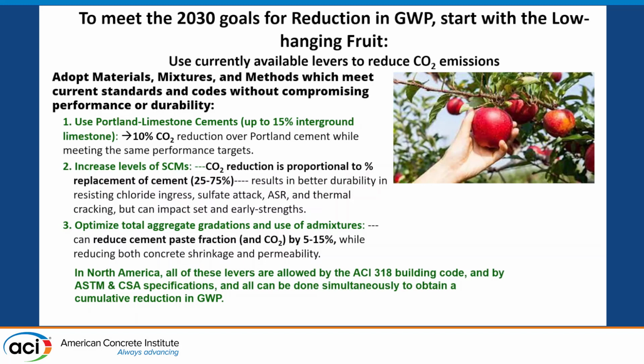So we can meet a lot of the 2030 goals for reduction in global warming potential by just doing things that are allowed now in the standard. Without making any changes whatsoever, we can do these things. We have Portland limestone cements with up to 15% ground limestone that offer about a 10% reduction in CO2 just by utilizing them.